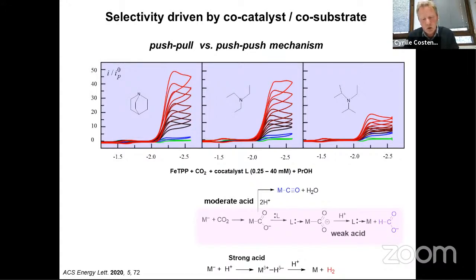So what is important here, and the conclusion would be, is that when you have homogeneous catalysis, you can control the reactivity by changing, of course, the catalyst. I have shown that if you change the substitution of the catalyst, you can make the reaction faster or not. But you also have to worry about co-catalyst and co-substrate that can drive the reaction in different directions, and especially what matters is the spatial concentration profile that you have close to the electrode. So it's important to understand that you have a two-dimensional reactor when you're doing homogeneous catalysis.